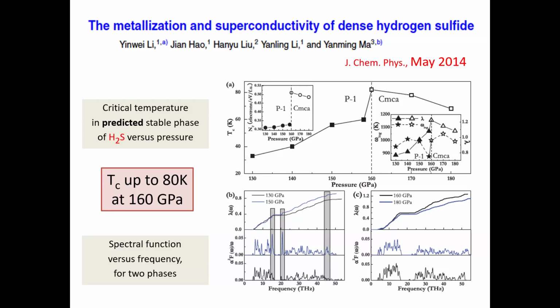And what he showed computationally, just computationally, using this well-developed computational theory, is that if you put the material under 130 gigapascal pressure, or 140, 150, 160, the stable crystal structure was very low symmetry. This is called P bar 1. There's only one symmetry operation in this crystal, very low symmetry. But at this pressure, there's a change, and a different crystal structure becomes favored energetically. And there is where he predicted, in this particular case, 80 degrees Kelvin superconductivity at 160 gigapascal. And this has now been found.